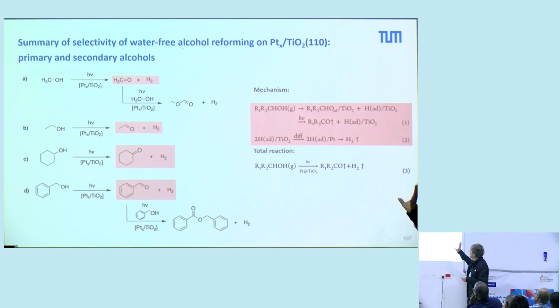There are cases, of course, where we are producing radicals on the surface. And if you have a defined temperature window, these radicals can combine. And so there are some alcohols with a product of the CC coupling, for instance, here or here. But we can also understand this with our mechanism, because we have these radicals on the surface which are migrating, undergoing CC coupling, and desorbing from the surface. But it is not the main product, and it is very dependent on the temperature. That means we can also use the temperature to tune the selectivity.